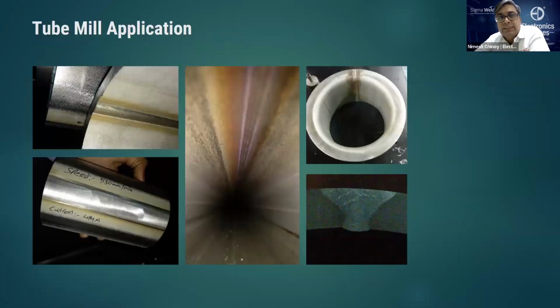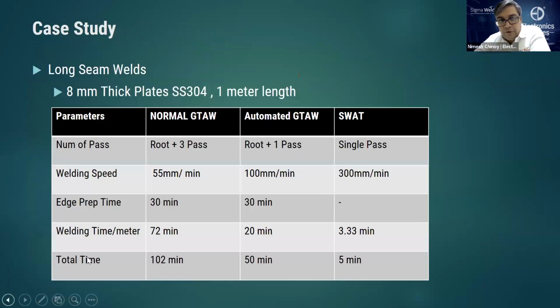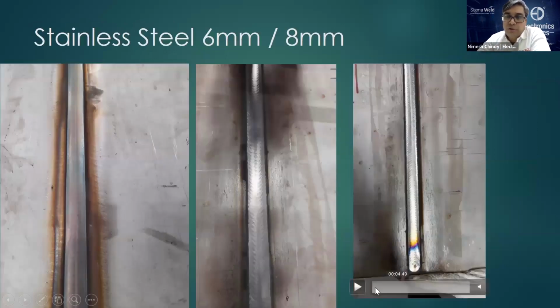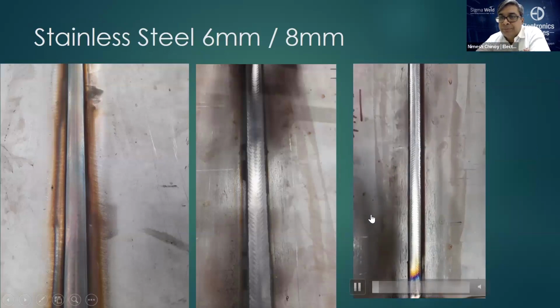These are tube mill examples, which have been done from 3 millimeters all the way up to 8 millimeters, continuous weld. If you look at the time consumed for a 1 meter stainless steel plate, if you were to do manual TIG, it would take you about 102 minutes. Automated GTAW, 50 minutes, and SWAT, 5 minutes. That's the kind of efficiency you can get. Not to mention no use of any filler material.